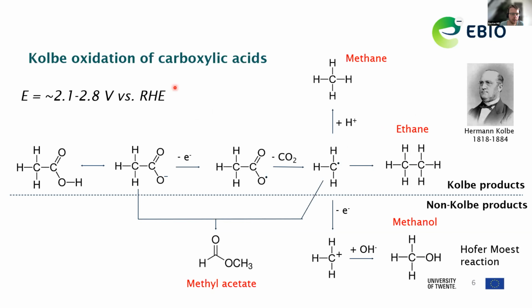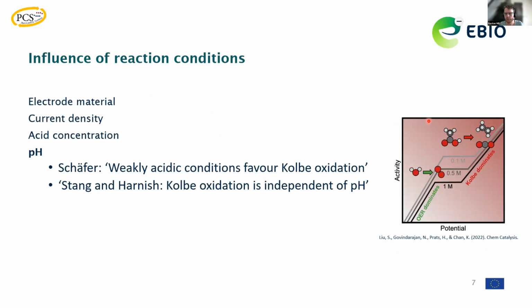So what is also shown here is that we need a potential at the anode which is way above the oxygen evolution potential. So to really make use of the Kolbe process, the oxygen evolution needs to be inhibited. And that's what is shown here on the slide. Usually what you observe in the presence of any of the carboxylic acids is that you first have an oxygen evolution regime, which is then terminated, and you have a plateau region after which Kolbe oxidation really occurs. And of course the intensity or the current density of this plateau region depends on the concentration of the acid that you're using here.